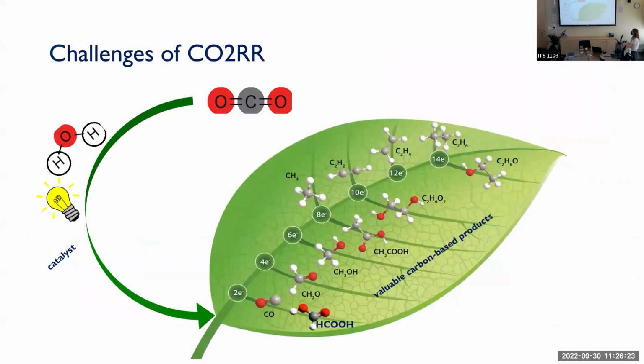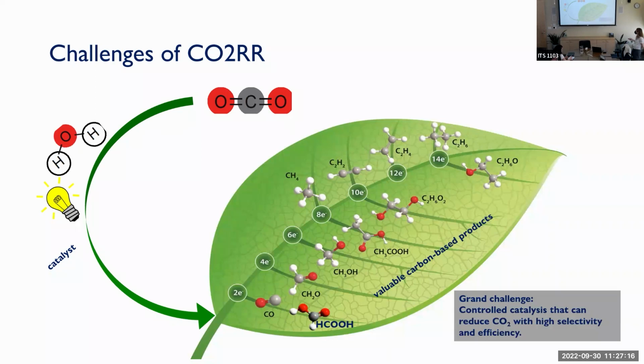Okay, sure. So I mentioned earlier the challenges of CO2 reduction. CO2 reduction is challenging in many different ways, but the first and foremost reason is that you can reduce CO2 to almost anything. And it's an issue if you start thinking about separation of the products and how you become efficient in a reaction. So you see here, depending on the amount of electrons that are involved in the reaction, of course, you want the highest number of electrons because these molecules are more energy dense than just carbon monoxide. But because you have so many electrons involved, the reaction becomes really unselective. And there is an opportunity there to control the selectivity instead.